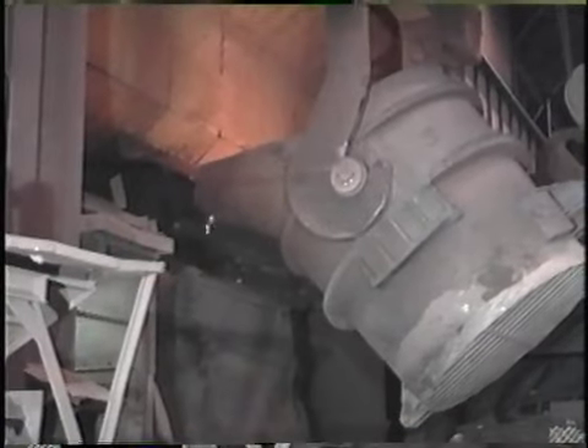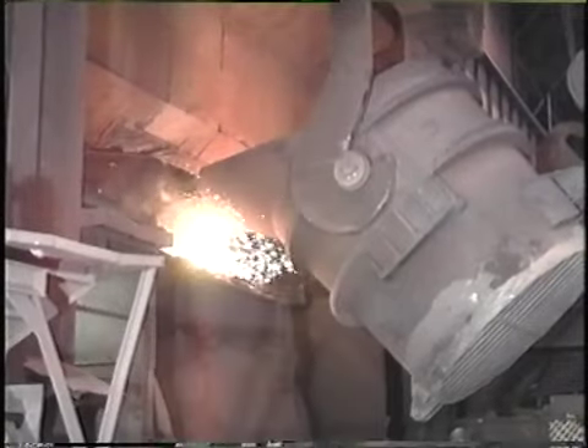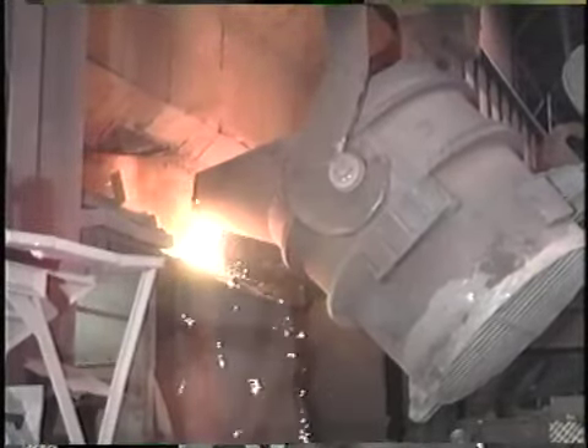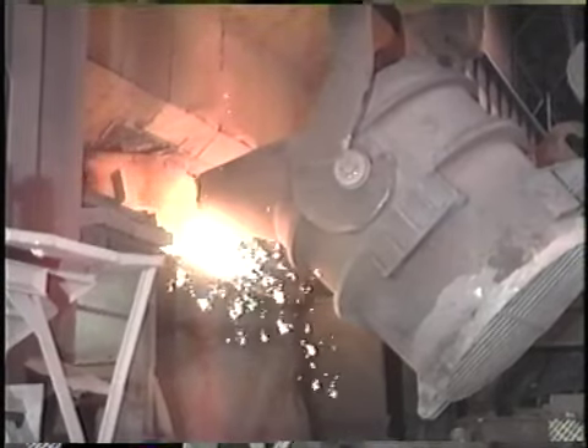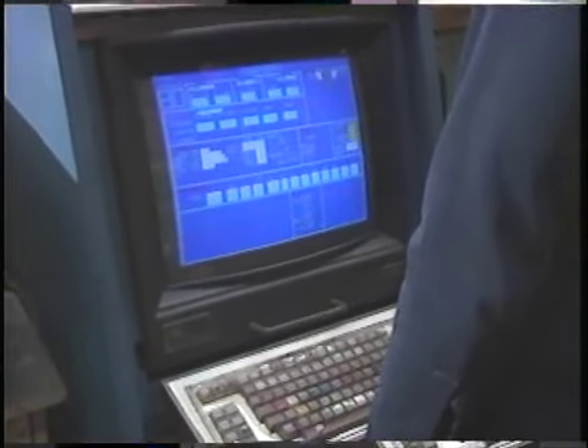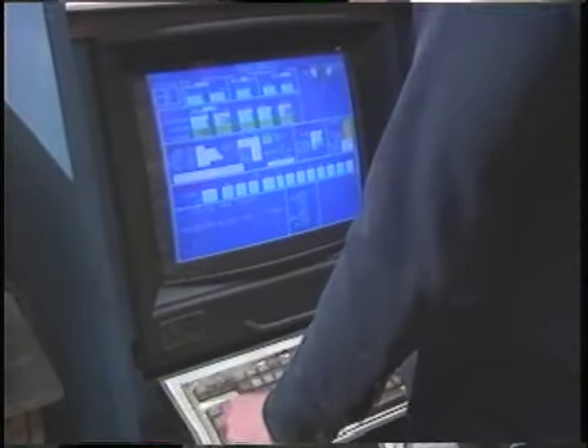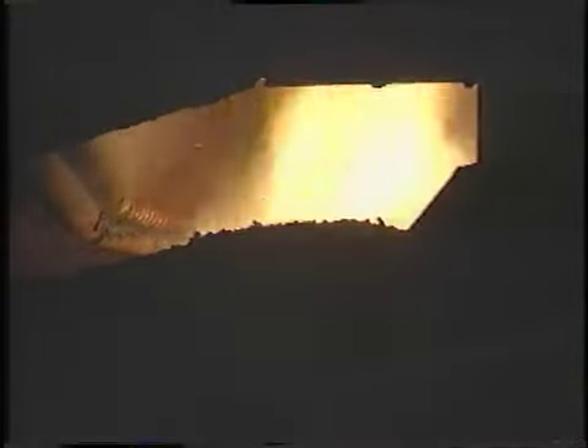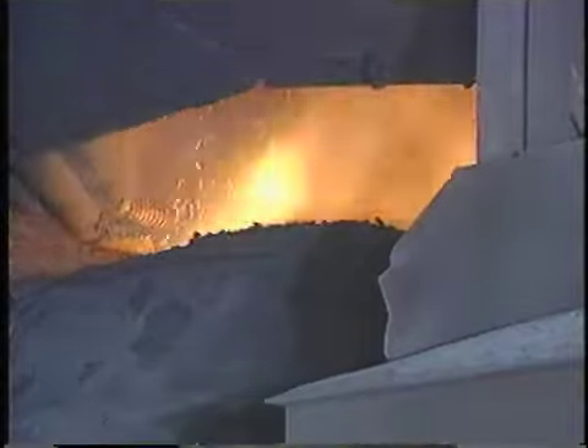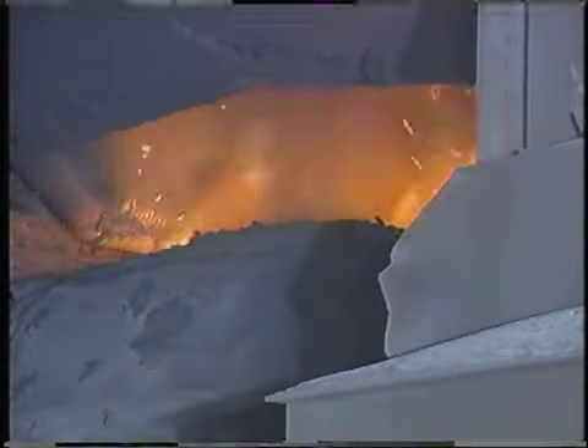Every 45 minutes, the BOF produces a 300-ton heat of steel. The vessel tilts to receive cold steel scrap and molten blast furnace iron. Here, a computer calculates a mathematical model to ensure the correct additions of fluxes and scrap for specific metallurgical properties. With the furnace upright again, large volumes of oxygen are blown into the vessel through a water-cooled lance. The oxygen quickly raises the temperature of the bath to 3,000 degrees Fahrenheit. This rapid oxidation reduces impurities in the molten charge and converts the iron to steel.